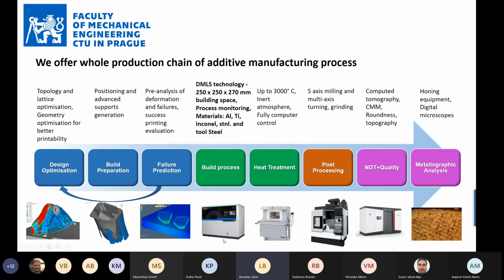Then I would say the print itself is only a small portion of the whole process. Usually you have to do some proper heat treatment, at least to get rid of the residual stresses, or with a lot of materials you can quench them or do precipitation hardening, depending on the material. Then for post-processing, usually when we care about the part, or it goes somewhere where it matters, you have to machine it, because hand post-processing is not sufficient regarding the precision of the final parts.